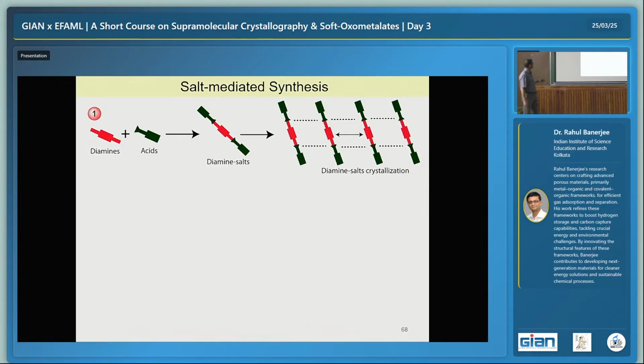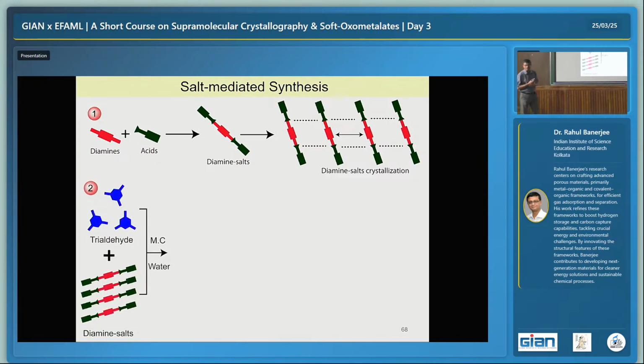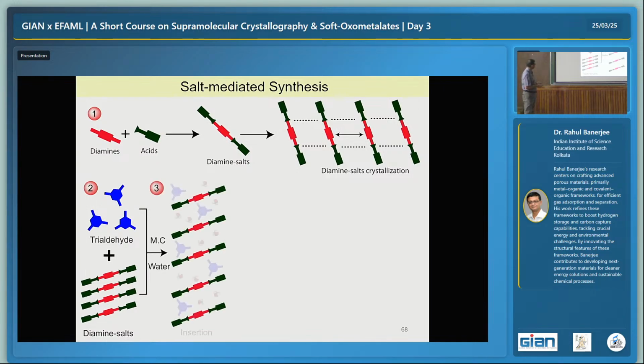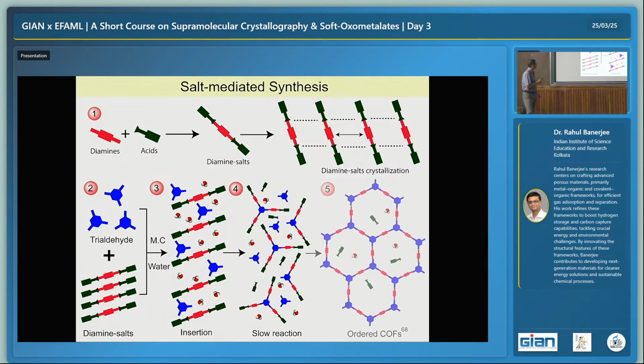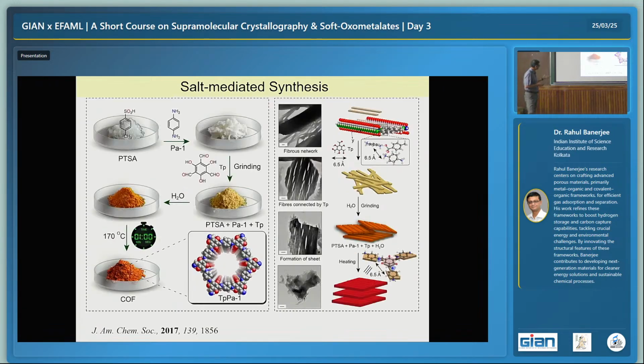So we tried to do that, and we used an organic acid, para-toluenesulfonic acid, reacted with this amine, and made a salt. Now what happened is that when the aldehyde came in, it has to first break that, or deprotonate that amine, and then it can react. So in this process, it gave us a little bit of time for the crystallization, and we felt that it will crystallize. That exactly happened. We took this process, and this process eventually led.